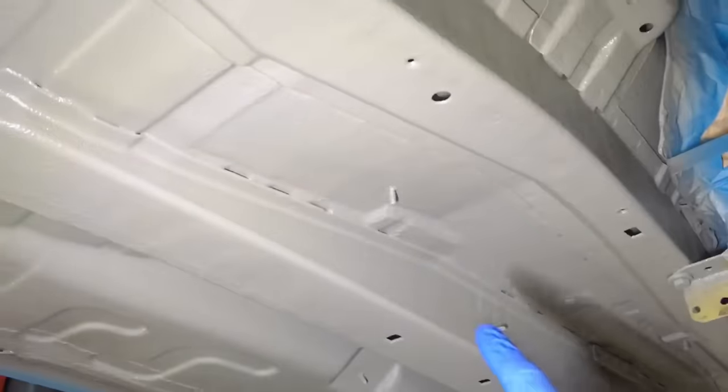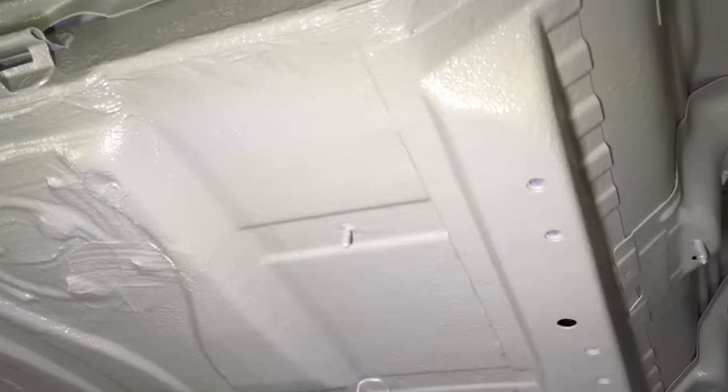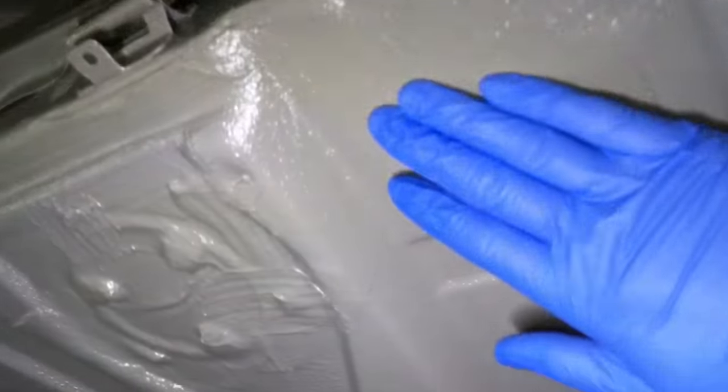This is the area here where the fuel pipes and the brake pipes go. This is the heavily dirtied area originally that had factory wax, which then got really dirty and holds the dirt. So that was all removed, decontaminated and neutralized, because if there was anything remaining, then the paints won't stick to that. But it has adhered really well. Nothing's coming off, it's extremely flat and perfect.